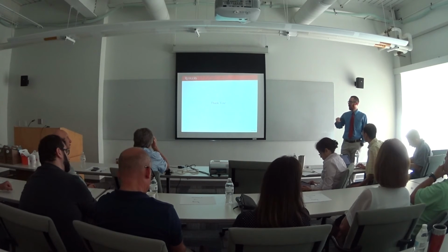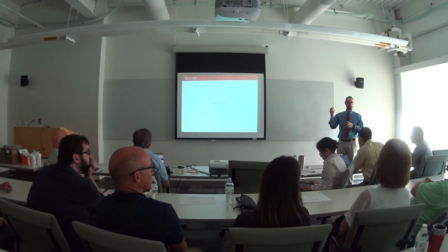It all depends on the complexity of your model. In general, if you have a curved surface, it has a different interaction with the system. However, in this case, we use just a really simple square well potential that has the same interaction regardless of geometry. So we basically restrict ourselves to this really simple case. If you had a curved geometry, you could introduce probably stronger interactions depending on the curvature. If it curves inward, it probably has a little stronger interaction, and if it's outward, probably a little less. But this model is not meant to take care of that.